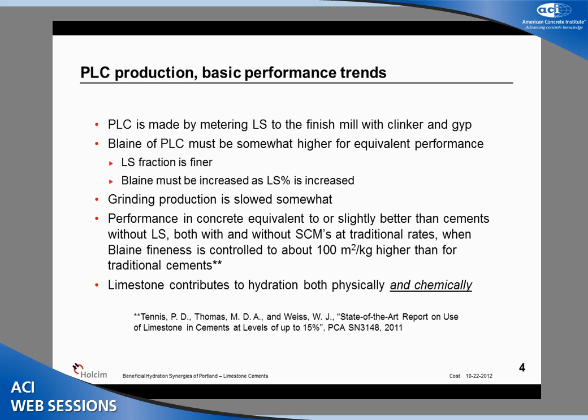As kind of a basic look at what Portland limestone cement is, this is simply the addition of some ground limestone materials along with clinker and gypsum to the finished grinding mills at a cement plant. Virtually any cement plant can do this. We do grind this product to a higher overall fineness than ordinary Portland cement, and this does slow production a little bit.